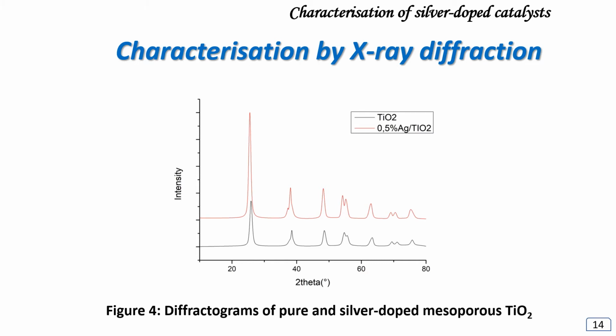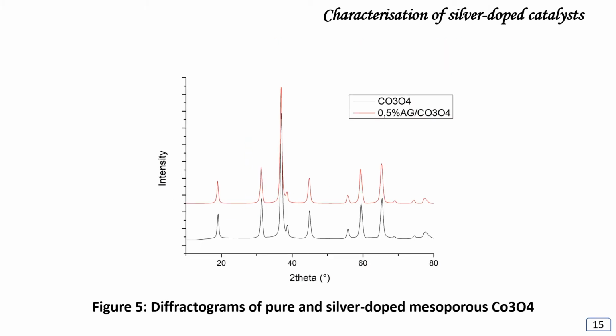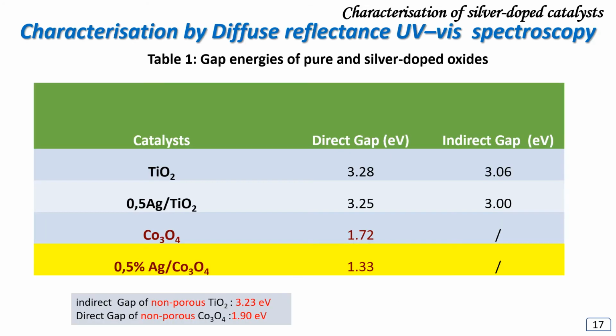doping. The diffractograms of Co3O4 and 0.5 Ag on Co3O4 show the characteristic lines of Co3O4 and that the structure is retained after silver doping. As for silver-doped titania, the characteristic silver lines are absent on these diffractograms, and the silver doping improves the crystallinity of the cobalt oxide. In this table, we note that the gap energies of mesoporous titania and cobalt